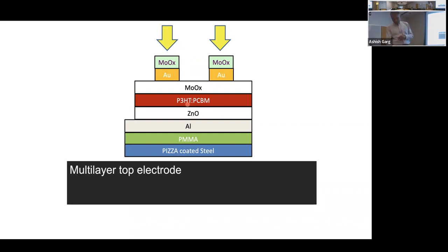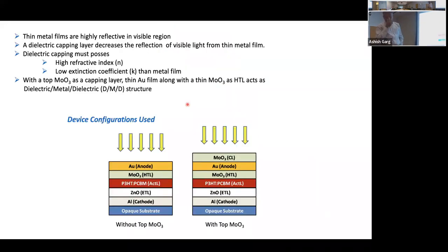So what we did was, the device configuration stays the same, but instead of using just a gold layer, we put a top layer of moly oxide to make it a dielectric. So MoO3 basically is a dielectric. So a dielectric-metal-dielectric stack results in higher transmission. So this is what basically the ground rules are.